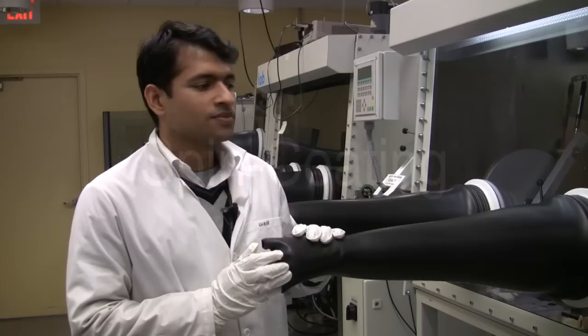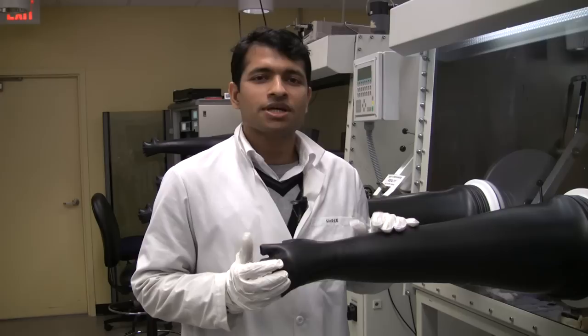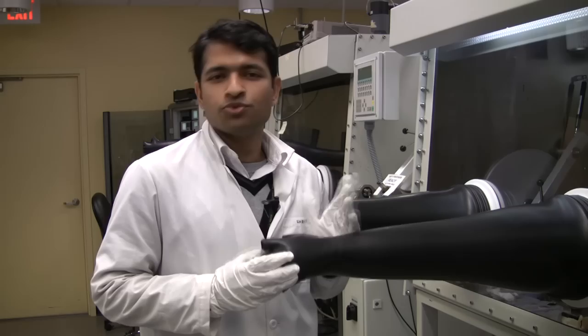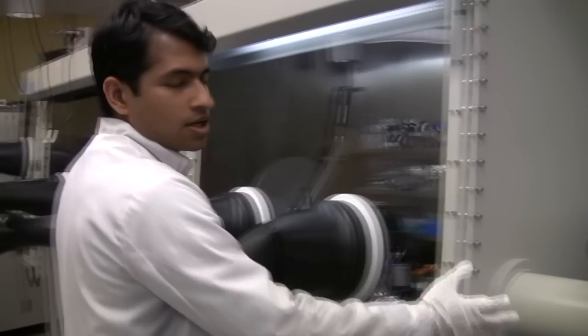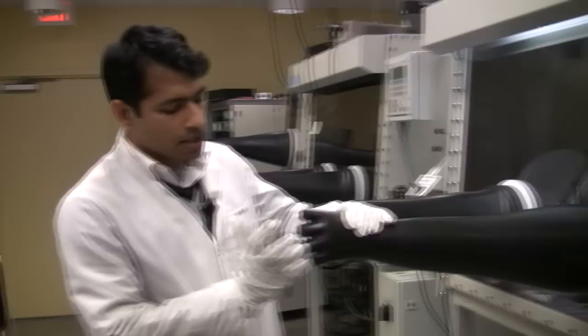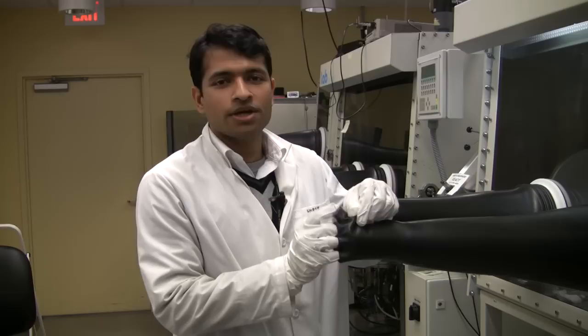So this is a nitrogen glove box. These organic semiconductors are very sensitive to moisture and oxygen, so that's why we have controlled environment in these boxes where we control O2 and H2O up to 0.1 ppm level. So basically we have the substrates ready and we transfer these substrates inside these glove boxes. And before spin coating, we need to have the semiconductor in controlled ambient so that they don't degrade and we have better devices.